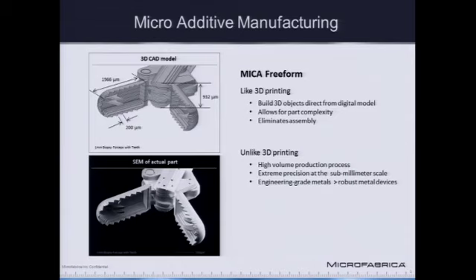But we're also slightly different than your typical 3D printing. We do parts in high volume. Because we make micro parts, we make parts in batch, in hundreds, thousands, 10,000s parts at a time. We hold precisions down to plus minus 1 to 2 microns. Again, most of our so-called competition is really standard conventional machining, and holding those tolerances can be pretty difficult. And we also use engineering grade materials, very high yield strength materials, which lead to robust micro devices.